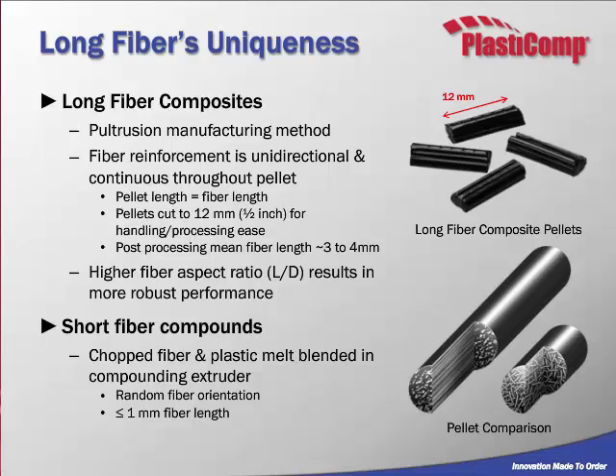Now why that's important we'll touch on in the upcoming slides, but with long fiber, because you start with a continuous strand, you are left with unidirectional reinforcement that is as long as the pellet you've chopped. And if molded properly, you can maintain a fiber length in the finished part that's up to 3 to 4 millimeters on average. Whereas by the time you get done molding a short fiber material, you're typically less than 1 millimeter in length. And again, we're going to touch on why that's important shortly.